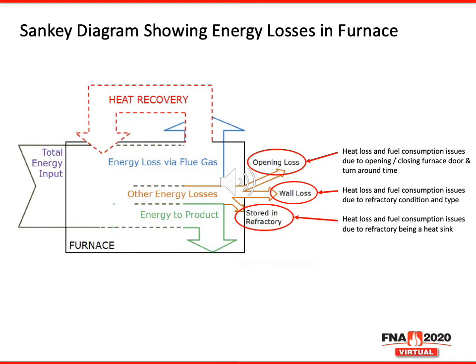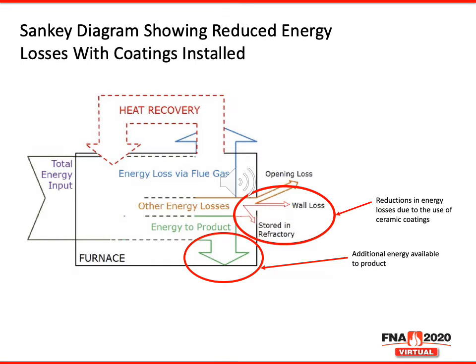The Sankey diagram shows us the energy losses that occur in a furnace. Knowing the total energy input, we can calculate the amount of energy available to the product, minus any losses due to door openings, wall losses, stored energy in the refractory, other energy losses due to flue gas or heat recovery systems. By completely coating the hot face of the furnace's refractory lining, we can now reduce the opening losses due to the doors, the losses due to the wall, which is the transfer of energy through the refractory lining, and that of the energy stored within the refractory. By reducing these losses, we now have additional energy available to the product.